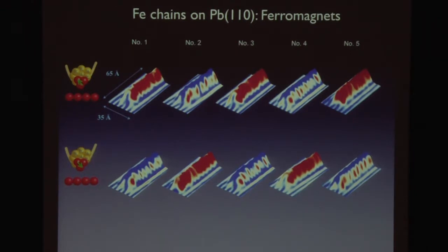So good. The electrons are localized to the iron atoms? So that's a good question. We believe that these chains are closely packed enough that you can talk about the band structure of this iron chain. But you cannot talk about it in isolation. It's coupled to the lead underneath. So you have those bands that I roughly drew for you for a simple ferromagnet. But think about them as blurred because they're coupled to another material which is non-magnetic and a different material.